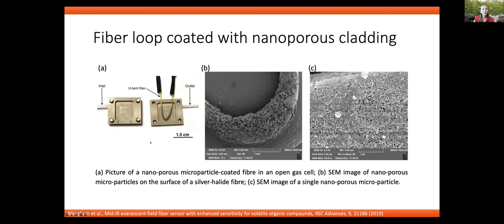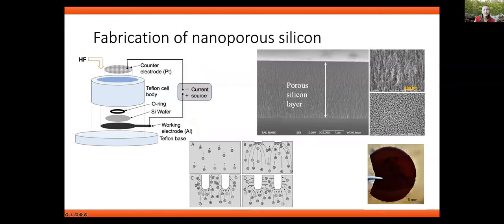So what we did now, we thought, okay, how can we use this stiff, effectively like glass, and very fragile porous silicon membrane in order to coat our optical fiber. And the reason why we want to use porous materials is because they increase the capillary condensation of the volatile organic compounds. So those are effectively like sponges that will take on all the VOCs from the surface and keep them inside the pores. And if we can put those materials on top of the fiber, then the evanescent field of the fiber will interact with our gas molecules.